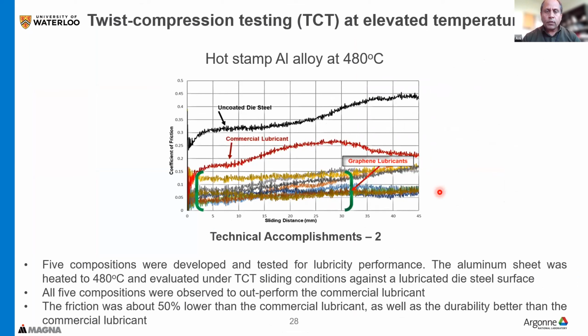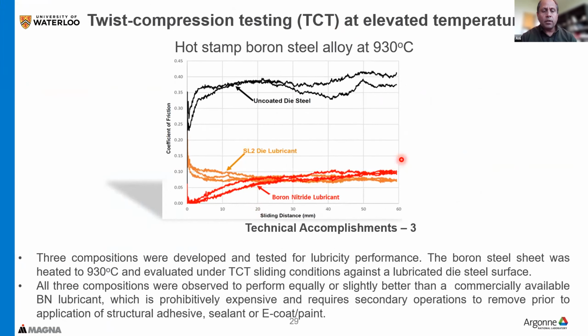And then we go to the higher temperature, again a comparison with the commercial lubricants, almost 50% lower than the commercial lubricants that we have seen here. And then this is at much higher temperature, 930 degrees Celsius. And then we are comparing here with the boron nitride lubricant. So basically our lubricant performs a little bit better than the boron nitride, but this is a very, very expensive lubricant, and it requires a lot of post-processing to remove it. So that's why I think our lubricant outweighs all the other things that the other commercial lubricants basically provide.